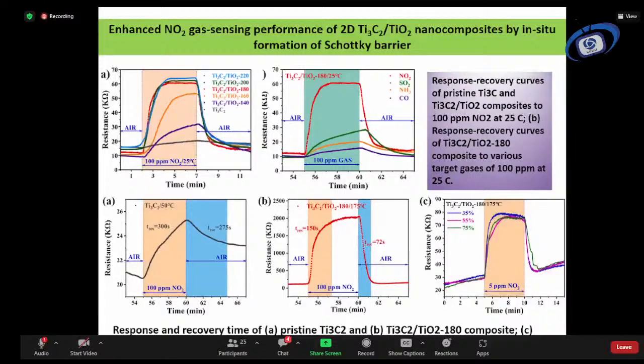Of course, this recovery time is very good, not that bad. Although in the recent sample we have achieved a recovery time of about 10 seconds. So that is a very sharp recovery time for that one. And we also tested our sample for different humidity, because these gas sensors are badly affected by